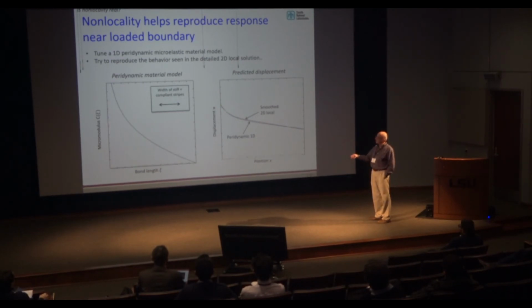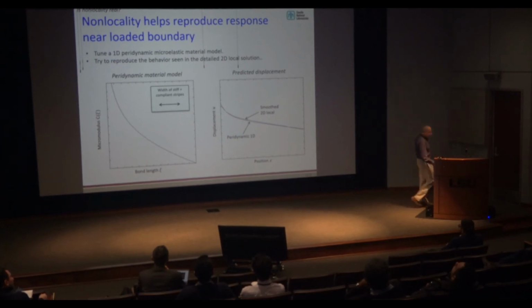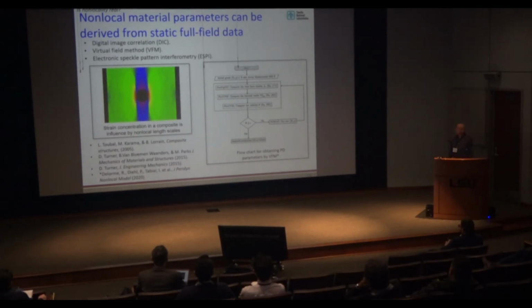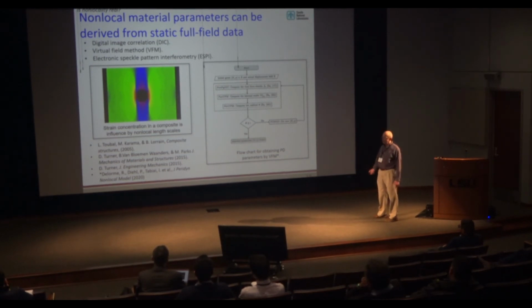And a micromodulus like the one shown turns out to reproduce this strange looking feature along the edge where the tractions are applied. So that's an example of where non-local helps you reproduce a homogenized small scale result. So can this be observed experimentally? Sure it can. If somebody wanted to do that experiment and do DIC measurements of the full displacement field, that would be another way to confirm, without resorting to this detailed computational model, whether or not non-locality has any role to play in the problem.